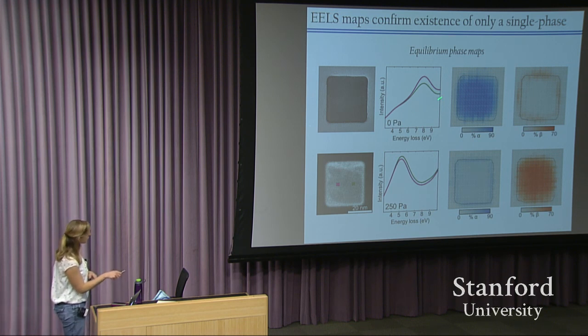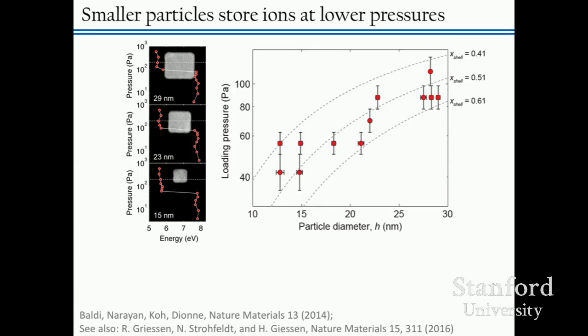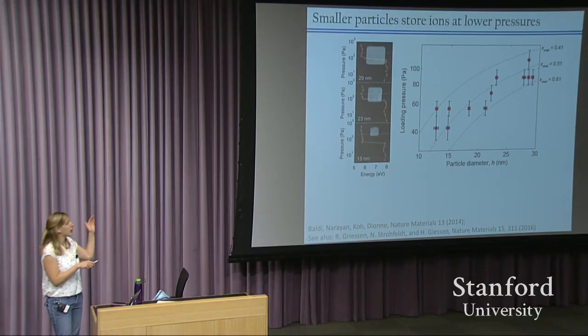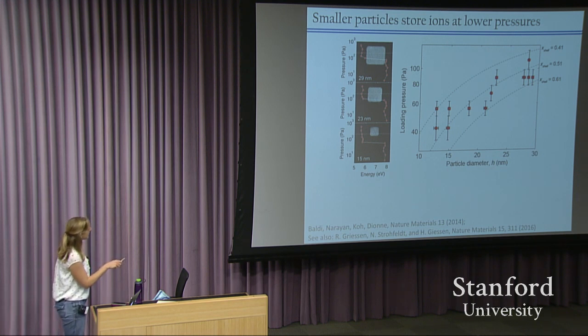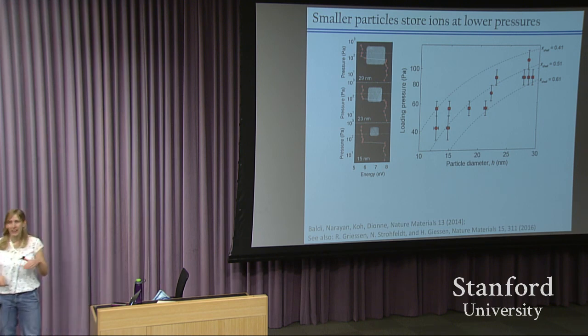And at low hydrogen pressures, the system is entirely in its alpha phase. At high hydrogen pressures, the system is entirely in its beta phase. So that was one trend that we saw from the isotherms. Another is that if we looked at the loading pressures for each of these nanoparticles and compared them with the bulk loading of hydrogen in palladium, these transition regions always fell well below the bulk alpha to beta phase transition. The bulk is shown as the white dotted line. You'll notice that the transition from the alpha to the beta phase in nanoparticles is always below that line.